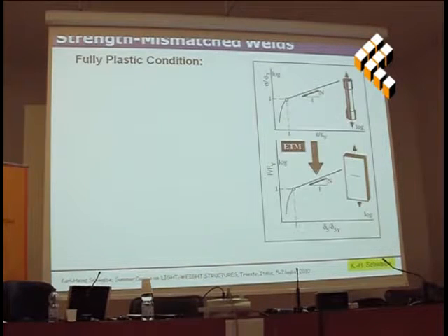And the idea is that here we have a stress-strain test plotted in double logarithmic coordinates. Here is the linear elastic Hooke's line, and before we reach the formal yield strength, there's already a little bit of plastic deformation, so there is some degree of non-linearity.